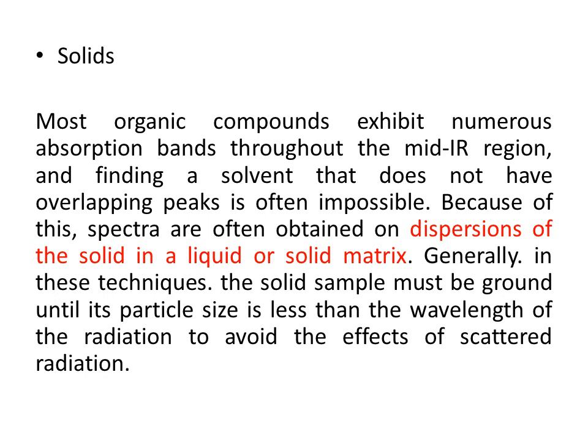Okay, and if you don't find any suitable solvent, then we have to go along with a dispersion technique. In it you don't have a limitation like UV, where you have to do the measurement in solution state itself. Here in case of IR we can do the analysis in dispersion state also. The only precaution you have to take into consideration is that when you are analyzing your dispersion, the particle size of your analyte has to be less than the wavelength of radiation.